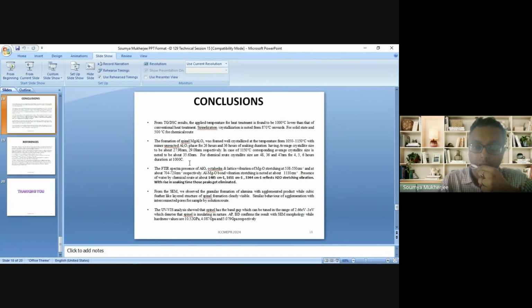And all particles are within the 50 nanometers range. FTIR spectra confirm the presence of the required metal oxygen coordinations, while we are getting some hydroxyl and H2O water stretching more in the case of the chemical route, due to the presence of chemistry and the water solution we are utilizing. We are also getting distinct structures. In the case of solid state we are getting some cuboid structures and some flaky structures, but in the case of the chemical route process we are getting more agglomeration tendency, and in some cases some interconnected cracks also.